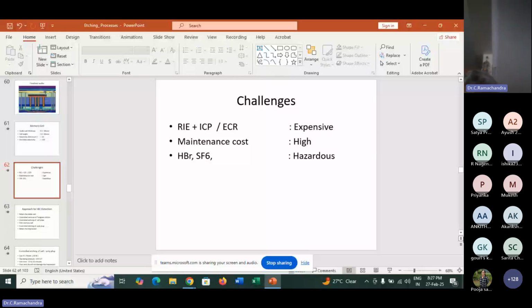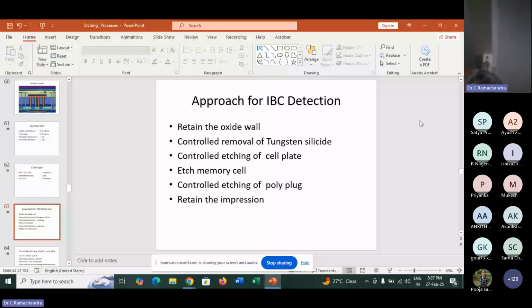And we have developed this technology for the first time. And this was the approach we have chosen: retain the oxide wall, controlled removal of tungsten silicide, controlled etching of the cell plate, etch the DRAM memory cell, controlled etching of the polyplug, and retain the impression. What we have to see is whether the impression is good or not.